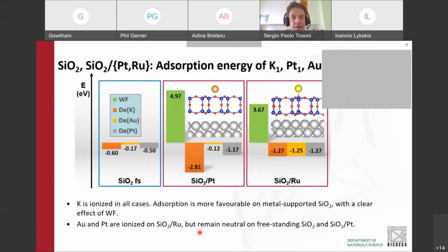If we move to silica, we have a case where on the freestanding film, all three atomic species are bound very weakly. And things change remarkably for the metal-supported silica bilayer. Here the work function is very large for silica on platinum and much smaller for silica on ruthenium. And for this reason, we have a much larger adsorption energy for potassium plus on silica on platinum compared to